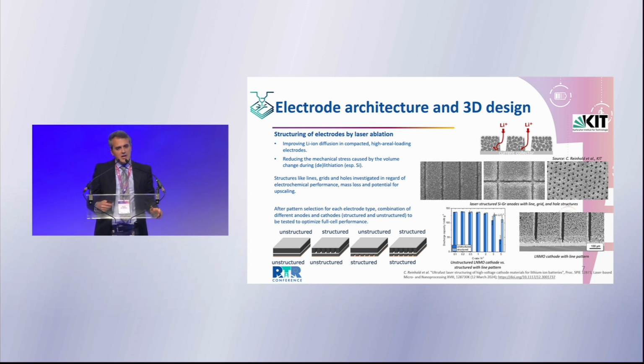To do so, together with KIT, we investigated the possibility of laser structuring the electrode, which, simplifying a lot, means basically carving a number of lanes, stripes, on the electrode materials. And we can imagine different patterns. We can imagine linear curves, some rectangular shapes, or some dots, basically. This laser structuring helps the diffusion of lithium-ion into the material, so helps the ability of extracting gravimetric performance from